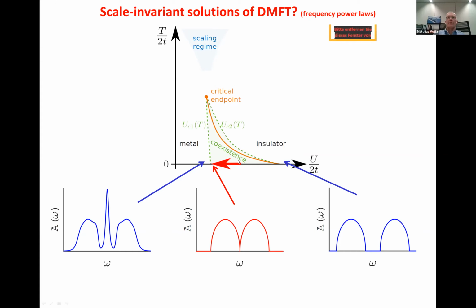That's true. As I just explained, this is a coexistence regime, and as with thermodynamic first-order coexistence, the two phases don't know anything about each other. Which means if you take the blue solution and go through this first green line, it doesn't notice anything, right? This is like with any first order coexistence. So if you have liquid gas and then you have a coexistence regime, but you take the phase which is stable through the line where the metastable phase disappears, the stable phase doesn't notice this.